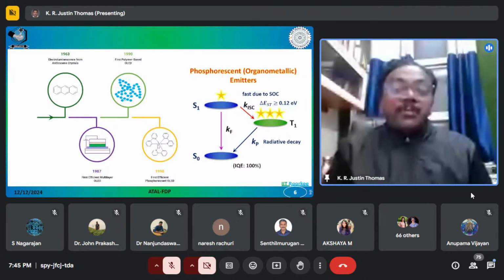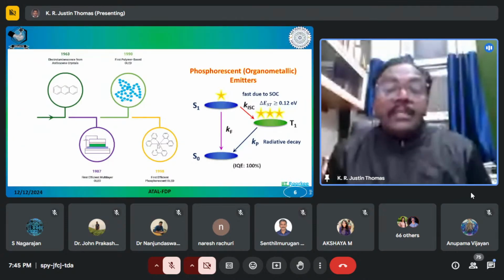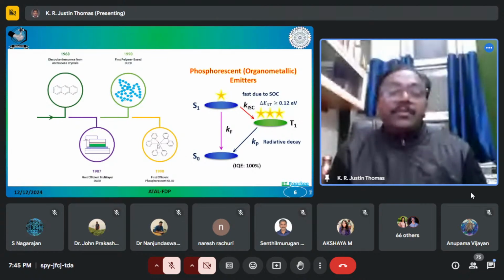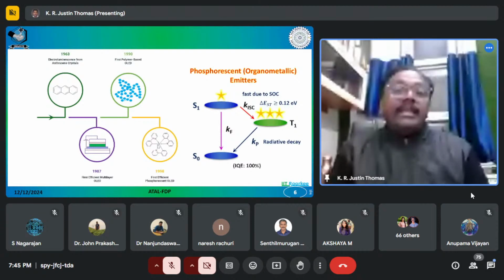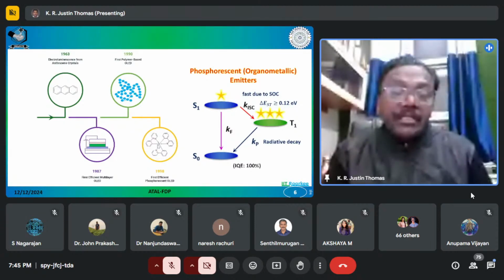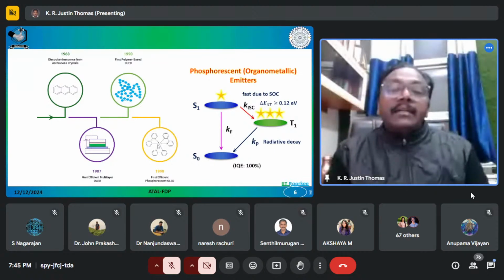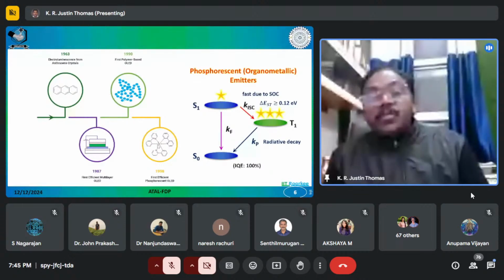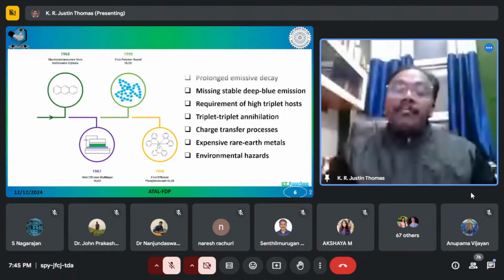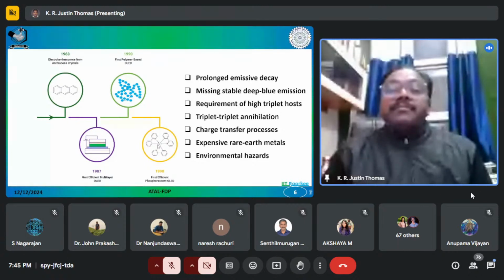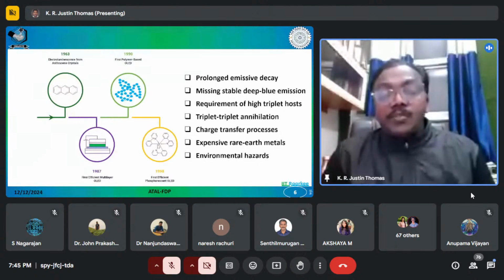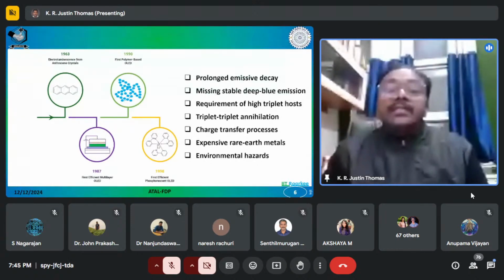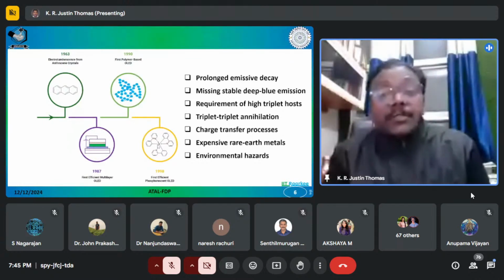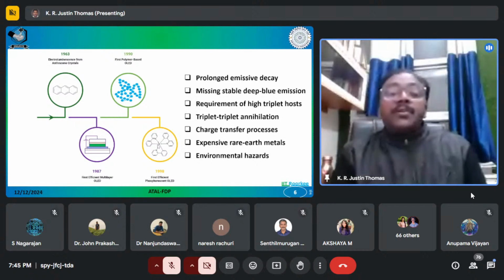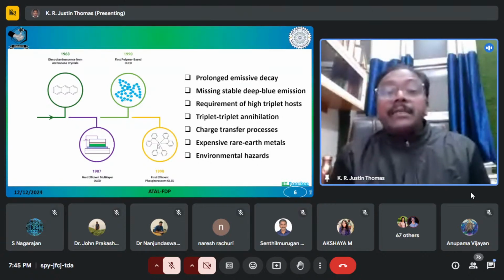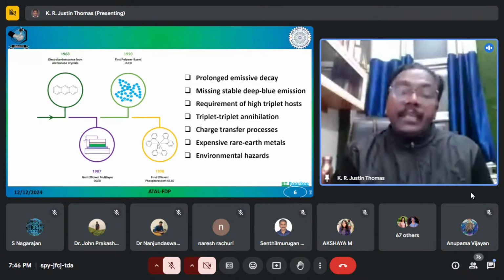So these phosphorescent LED devices are made by doping these iridium complexes in polymer matrices. This increases the cost of the device. It increases the processing time, the manufacturing time of the device. So that is one of the problems. But at the same time, most of these compounds have a long, prolonged excited state lifetime. That also leads to a lot of complications. You will have a lot of side reactions taking place. And most of these compounds have a metal to ligand charge transfer, and you know that this metal to ligand charge transfer is very weak. Because of that, the emission quantum yield of these complexes is also very low.